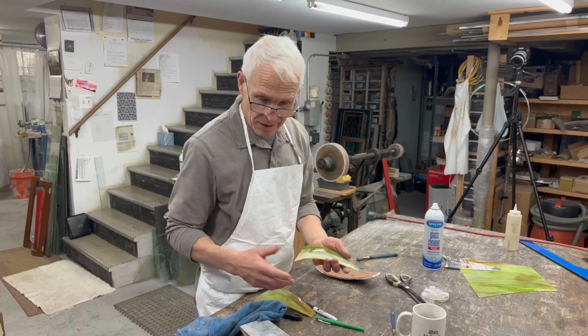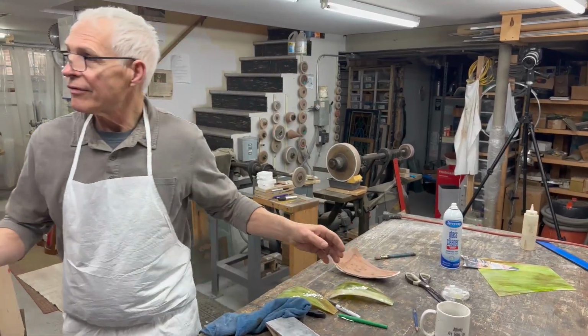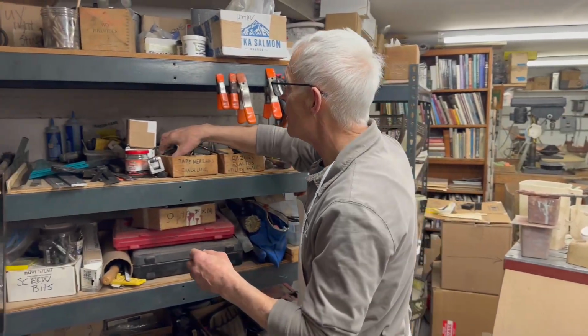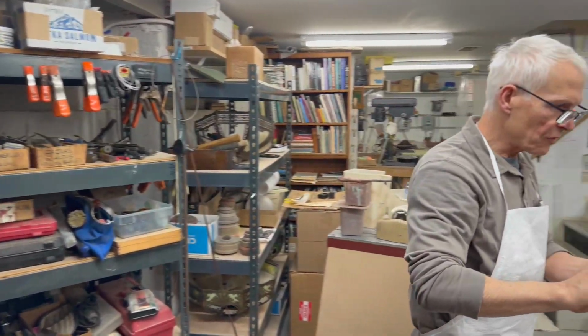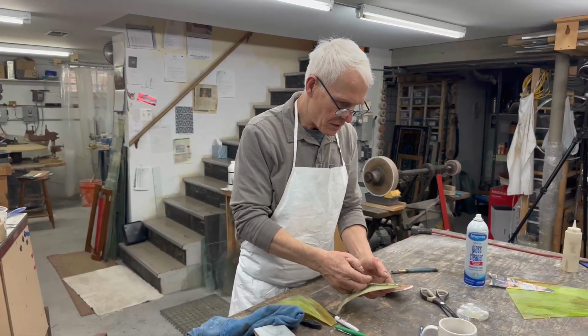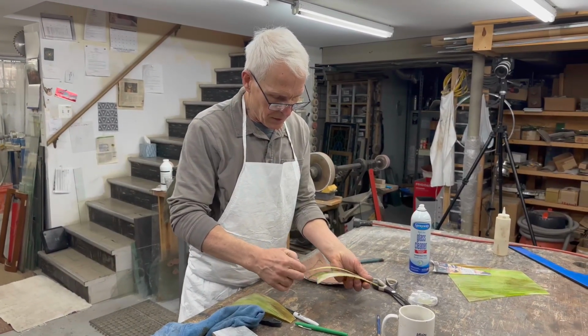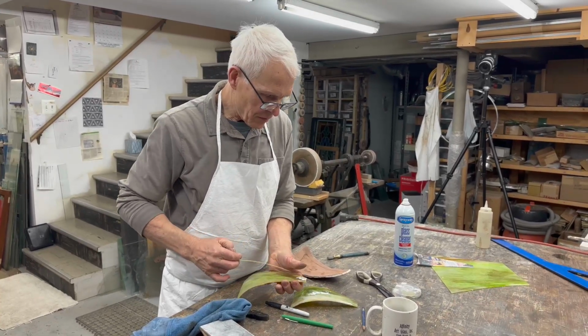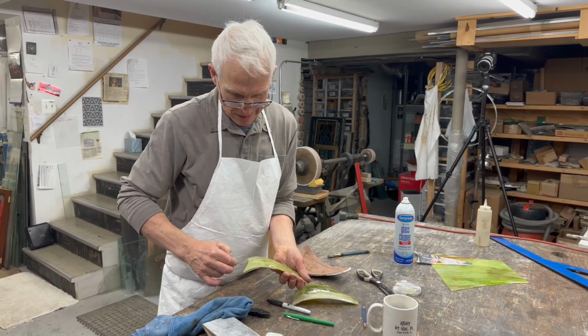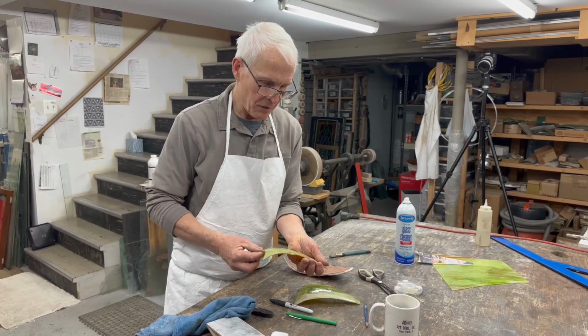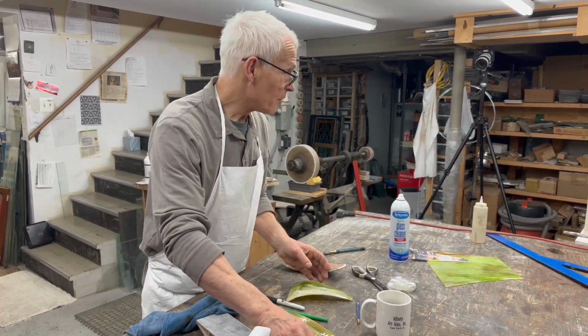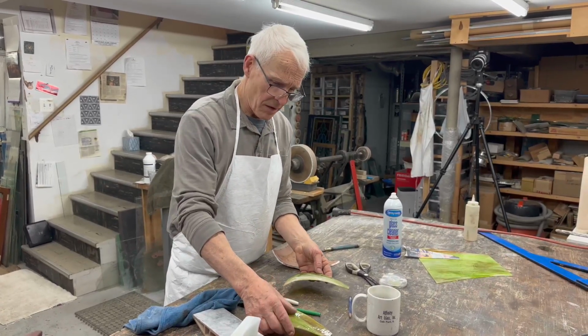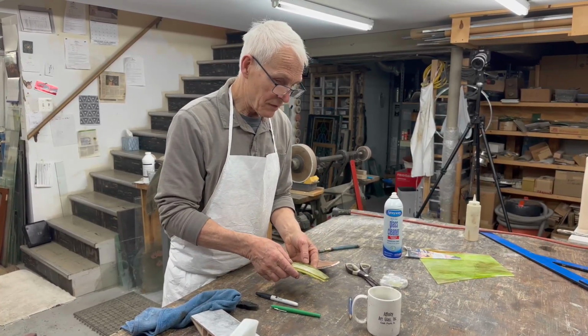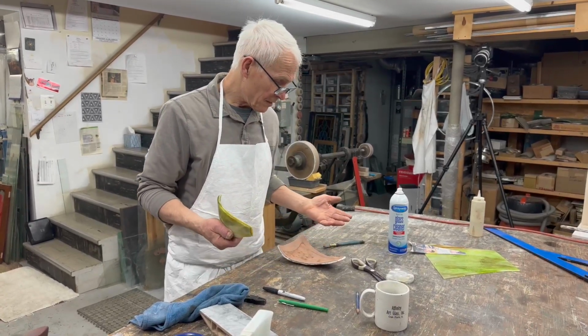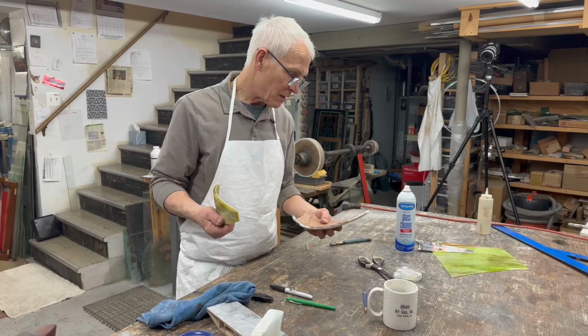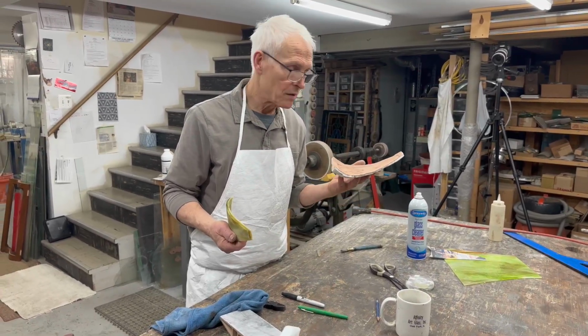grinding it too much. And then you can always resort to a flexible, like 1/4-inch tape measure to measure the length, and then make sure you're, this is actually, we've got to take a 1/16 off of the new one, which is not a problem with all the grinding equipment that's out there. So that's a successful glass slumping project with a ceramic fiber mold.